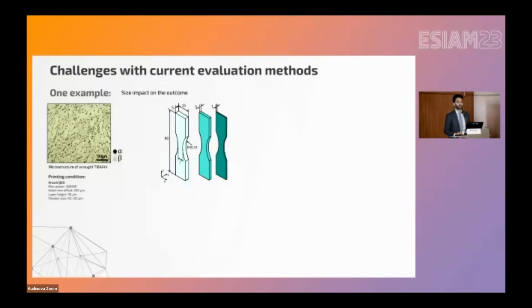Okay, we wanted to see how this size and scale can affect the mechanical property. In the first step, we saw this parameter in 1D, meaning thickness. Very simple. The material was titanium grade 5. The fabrication technique was EBM, and we considered three thicknesses, 1, 3, and 5 millimeter. So you see the range is not even large. This is a work we did 4 or 5 years ago.